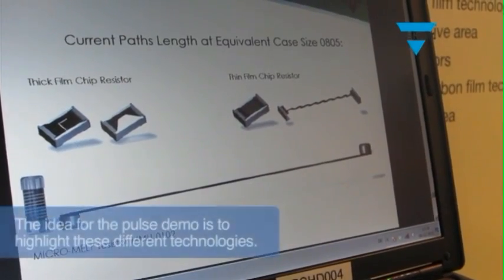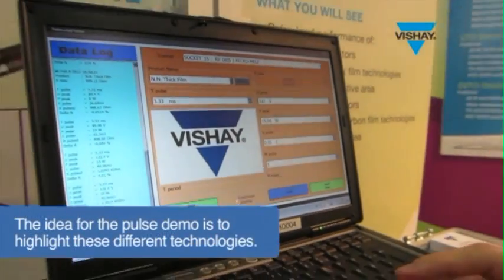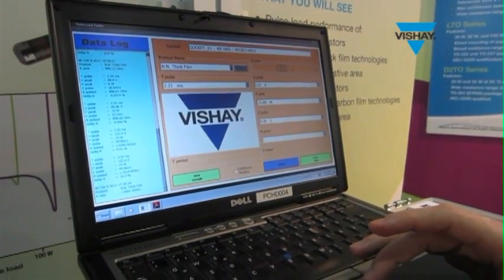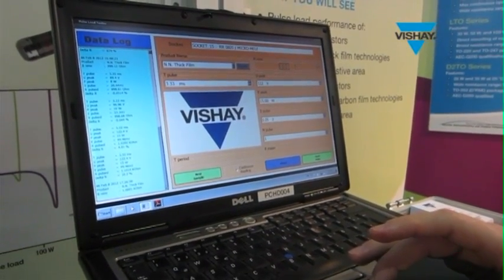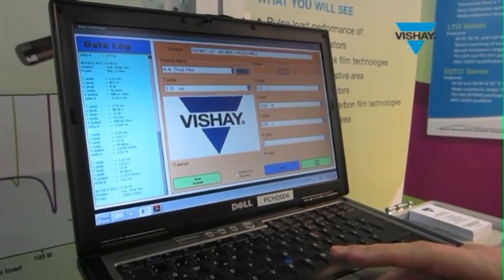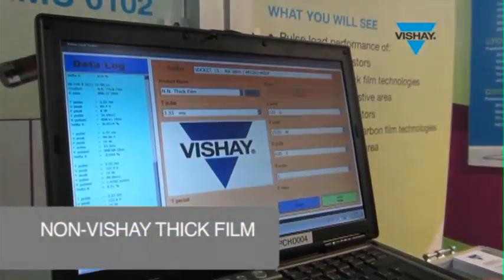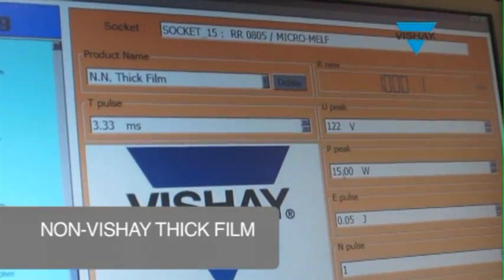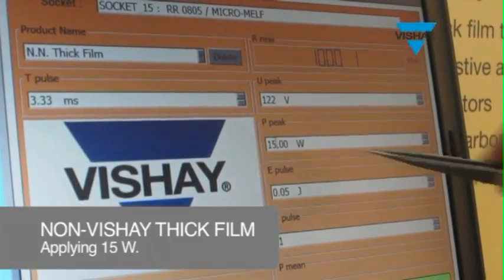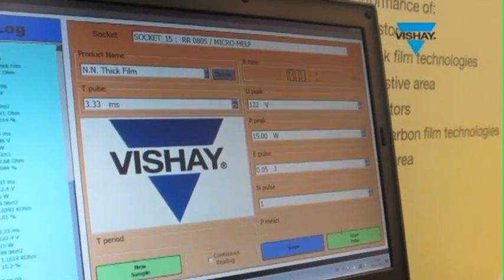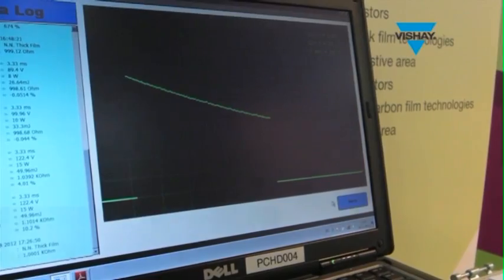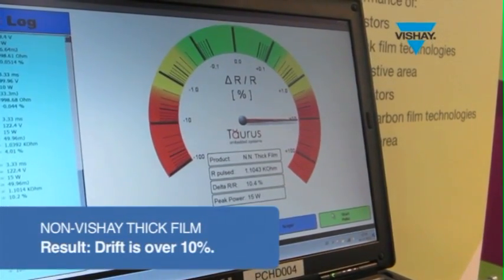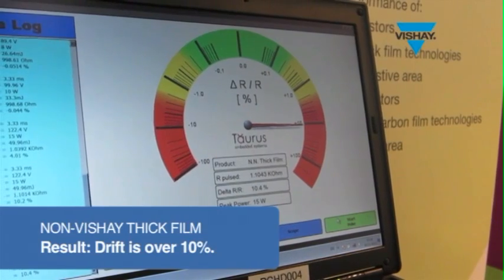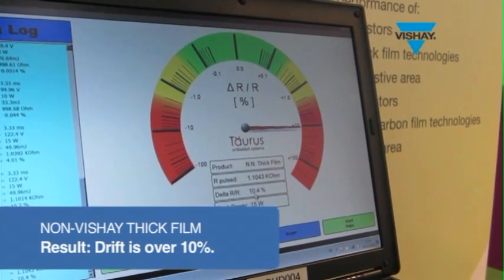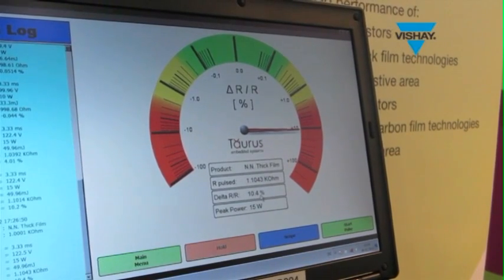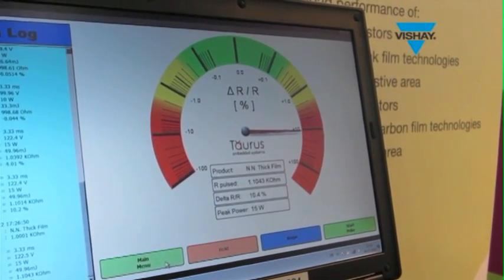And the idea of the pulse demo is to highlight this difference. How do they perform under some kind of surge requirements? The first component here is the non-name thick film resistor. It's a non-Vishay component using thick film technology, and we are going to apply 15 watts, as you can see here. Let's see what happens to the non-name thick film resistor. So 15 watts is enough to cause a resistive drift over 10%, which means that this component is no longer in working condition.